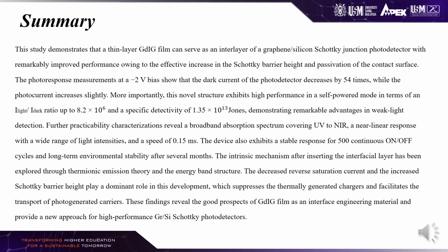Further practicability considerations reveal a broadband absorption spectrum covering ultraviolet to near-infrared, a near-linear response with a wide range of light intensities, and a speed of 0.15 milliseconds. The device also exhibits a stable response for 500 continuous on-off cycles, and long-term environmental stability after several months.